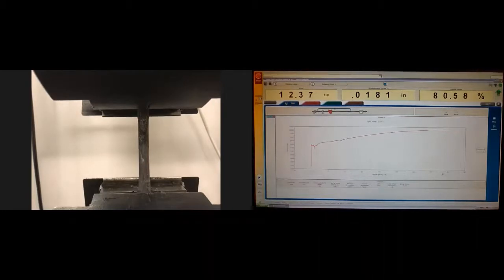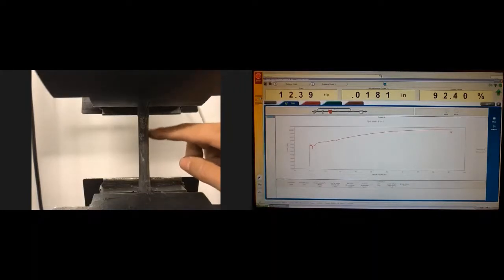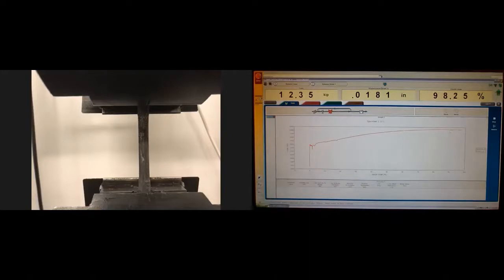So when we now see the curve being slowed down, it means that we will see the maximum force that this material can still handle. And at that point, the homogeneous deformation will change to inhomogeneous. And what it means is that we will start seeing some necking. And the neck will soon appear somewhere in the middle, indicating the weakest location of the sample. And there, the deformation will be localized at some point. Yes, indeed, it's now declining. And the neck will start to emerge and be more pronounced somewhere here real soon.